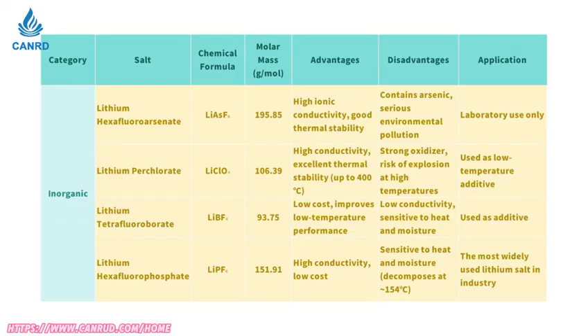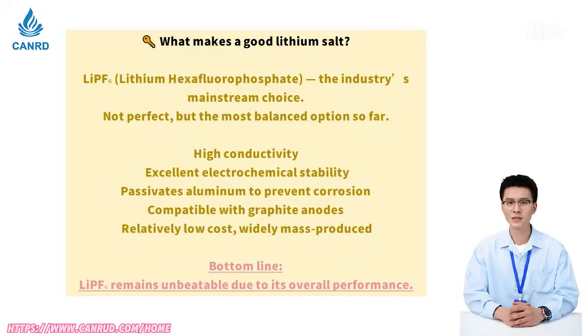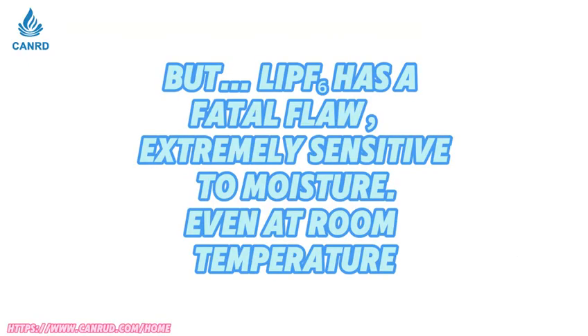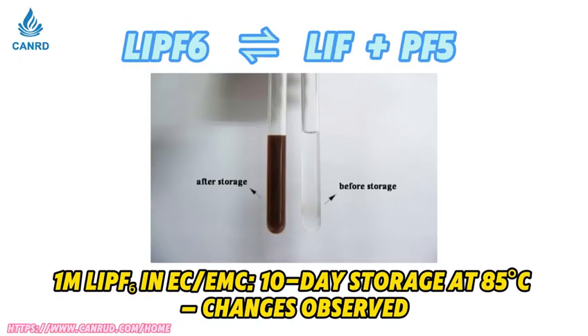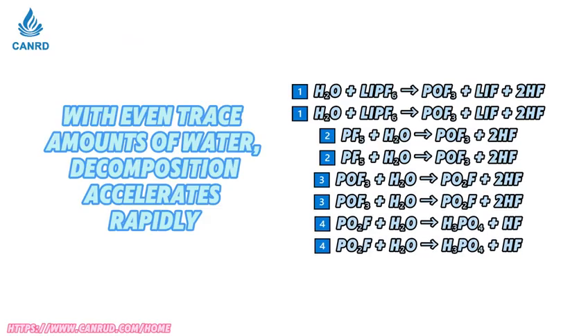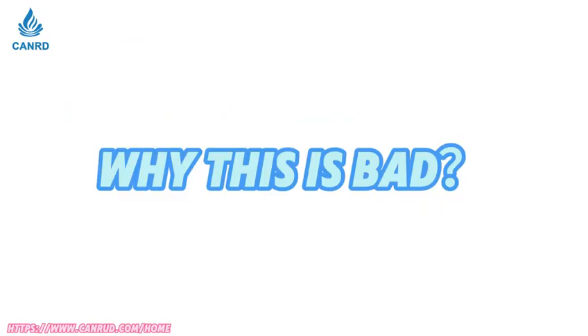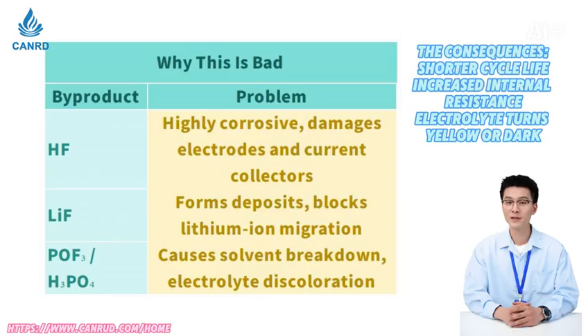High conductivity, excellent electrochemical stability, passivates aluminum to prevent corrosion, compatible with graphite anodes, relatively low cost, widely mass-produced. Lithium hexafluorophosphate remains unbeatable due to its overall performance. But lithium hexafluorophosphate has a fatal flaw. Extremely sensitive to moisture, even at room temperature, LiPF6 slowly decomposes. With even trace amounts of water, decomposition accelerates rapidly. Why is this bad? The consequences: shorter cycle life, increased internal resistance, electrolyte turns yellow or dark.